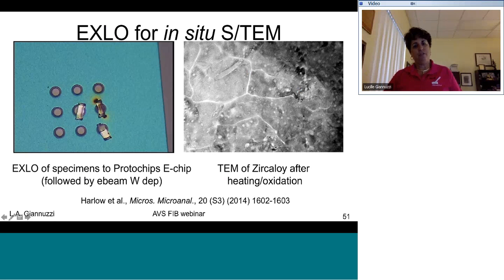ex-situ lift out of these samples, subsequently put back in the FIB to tack down the samples using E-beam deposited platinum, not ion beam platinum, because you don't want to ion damage your samples. And this just prevents drift during the heating experiment. And then this was done in an environmental TEM. So you've got an oxidizing environment at heat, and you can see then oxidation at the green line.